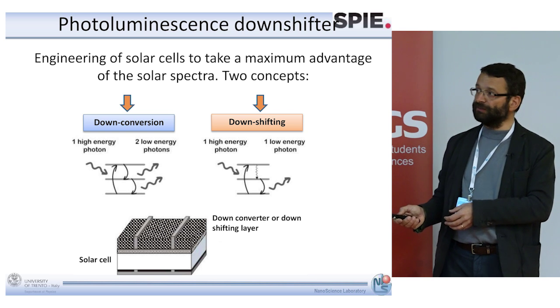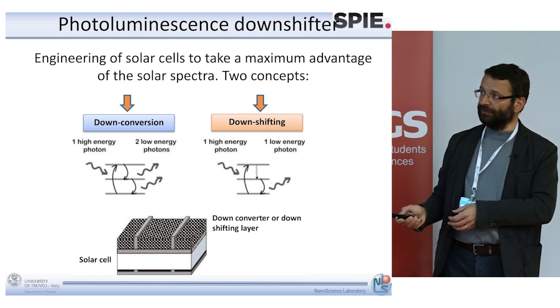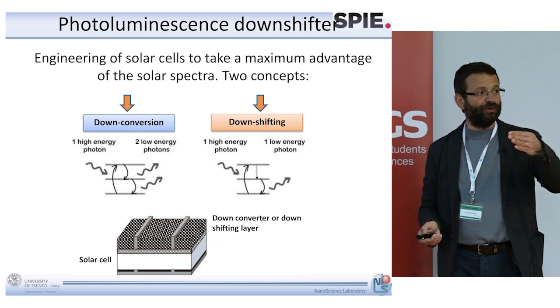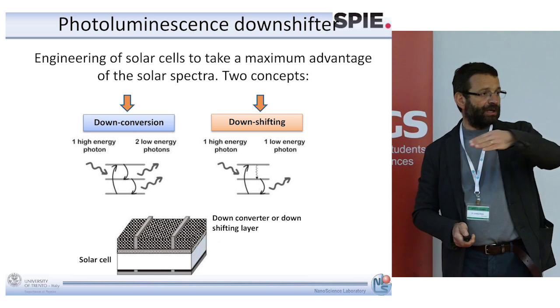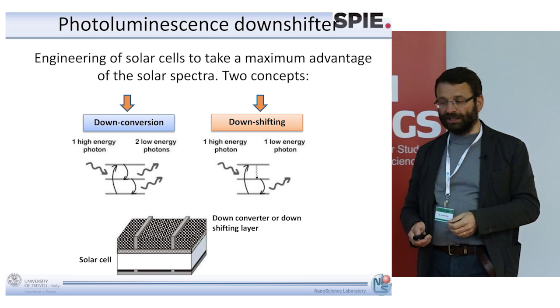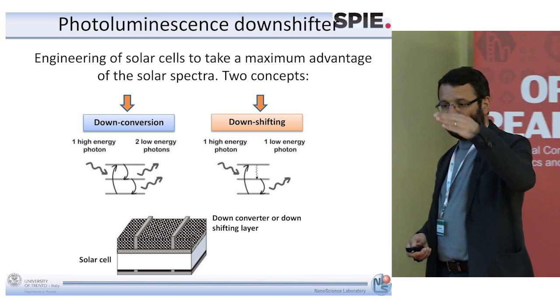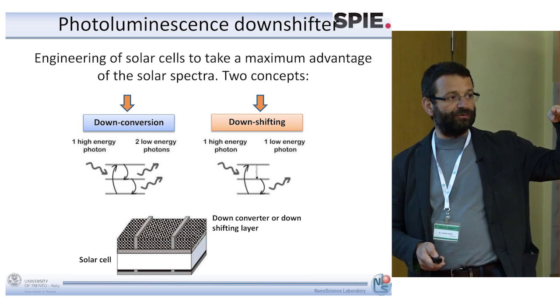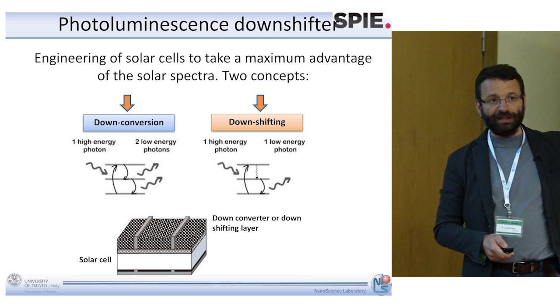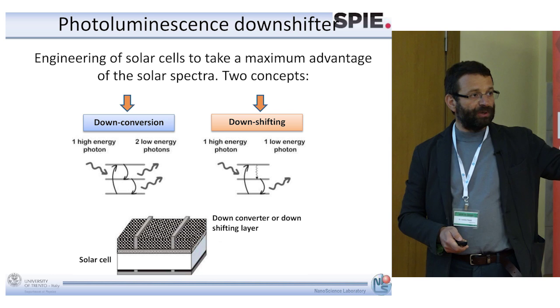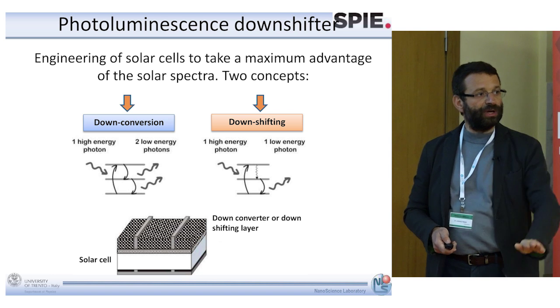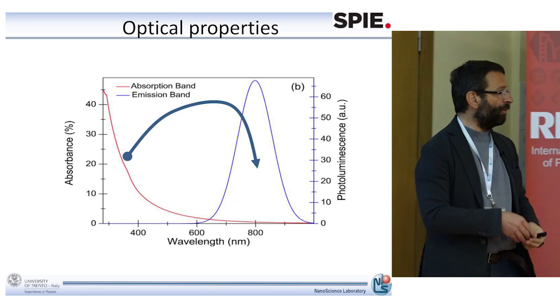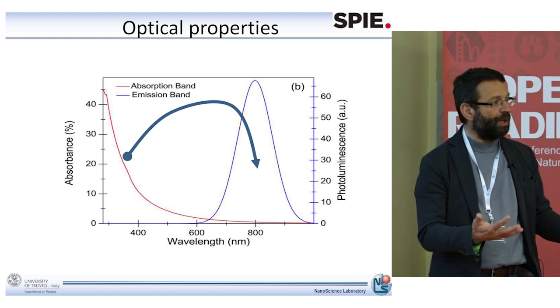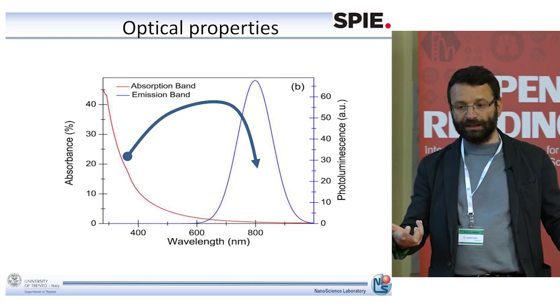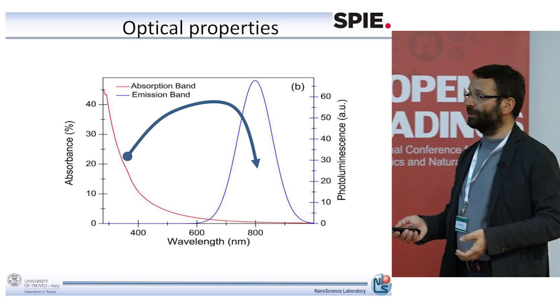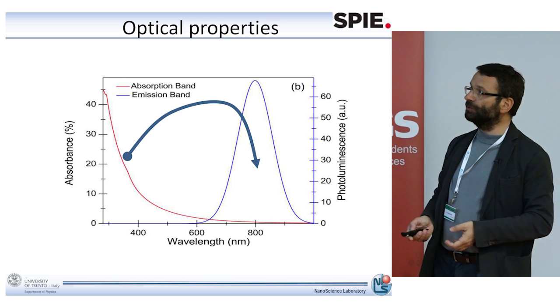And the reason is very simple, because in silicon, if you absorb blue photons, those blue photons are near the surface where defects exist, and so most of the electron hole pairs recombine on the surface. And so the efficiency of the silicon cell is lower in the blue than in the red. In the red, you excite more deeply in the silicon where fewer defects are there, and so you can effectively get a current from those electron hole pairs. And so this is what we want to do.